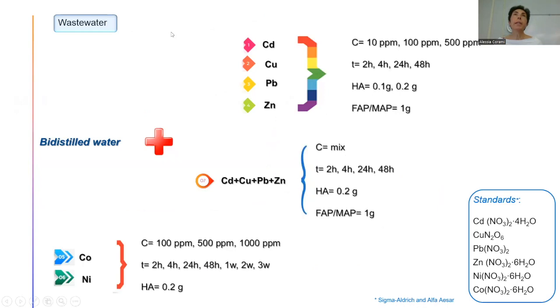So we started to create what we can define as wastewater, starting from the Italian legal limit for the amount of heavy metals that we can find in water, and then we increased the concentration. So our concentration starts from 10 ppm to 500 ppm, with a contact time from 2 hours to 48 hours. Then we decided the amount of hydroxyapatite between 0.1 grams and 0.2 grams, and for the two fluorapatites only 1 gram. In this particular case, the amount of phosphate is not really high. We want to study if we can add other phosphate later, or if this amount is too high and creates problems for the environment with eutrophication.